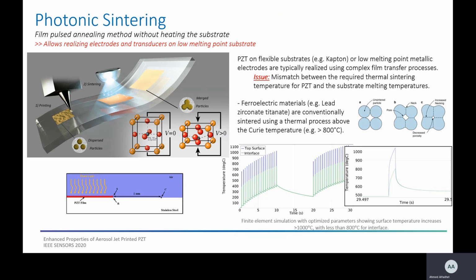COMSOL, a finite element thermal simulation, was conducted to get an idea about the heating at the top side of the sample and then at the interface. It was noticed that with 1 millisecond pulses for a period of 30 seconds, 2 cycles, we obtained 1000 degrees heating at the top surface, while only reaching lower than 800 degrees at the interface. By having very short spikes, we limit the potential for substrate melting due to thermal response times.